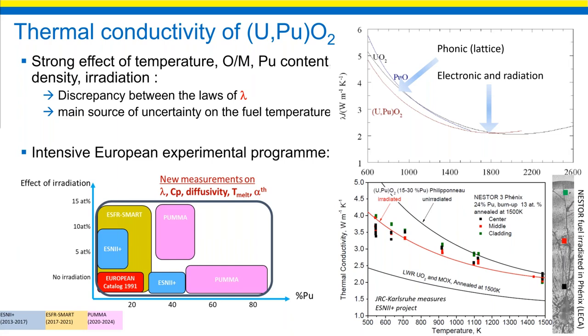On the right side, you can see the first data of thermal conductivity performed on irradiated MOX fuel for fast reactors. There are no large differences observed between the three investigated radial positions. We have a slight decrease of the thermal conductivity at the same temperature, observed from the center of the pellet to the periphery, which is associated with an increase of the burn-up and an increase of the plutonium content.